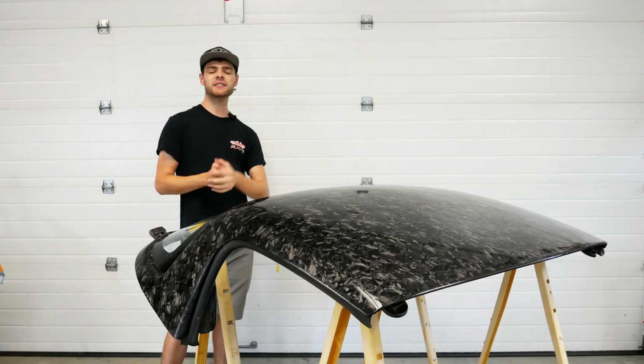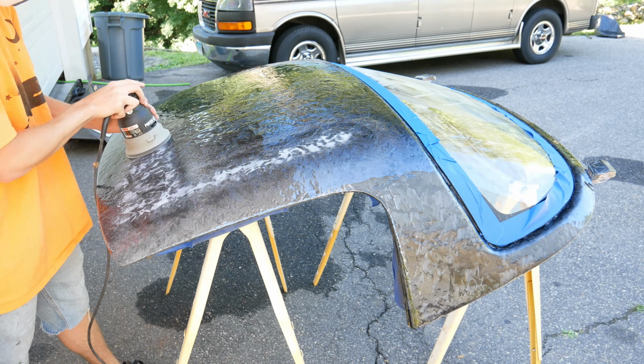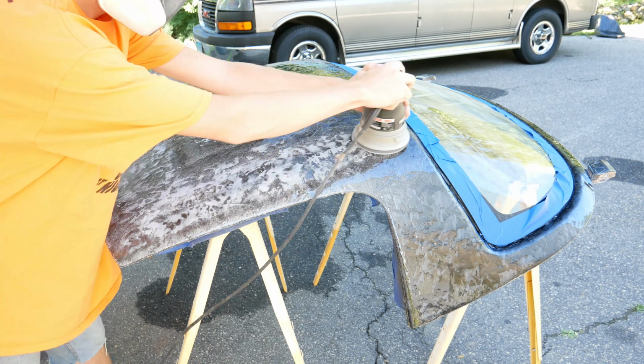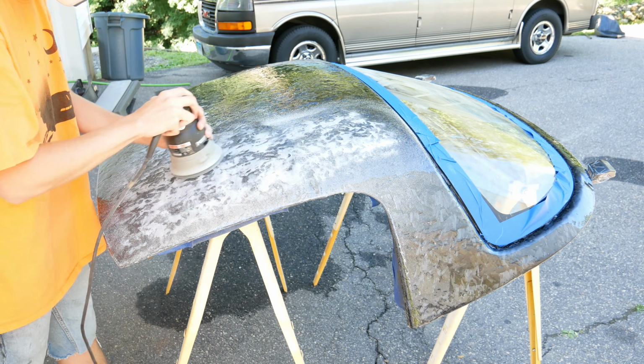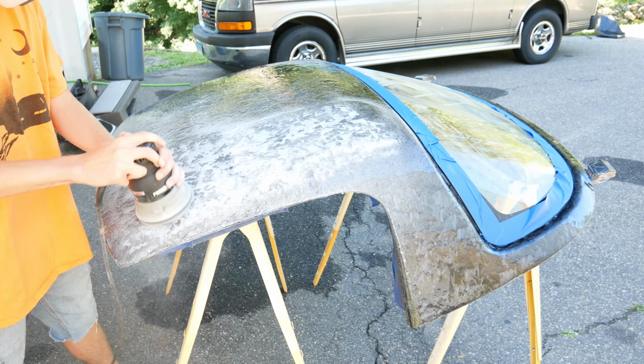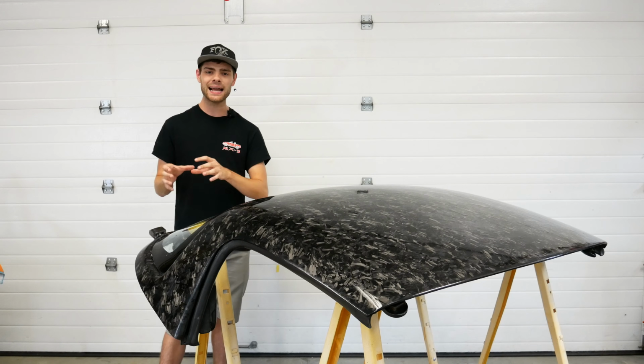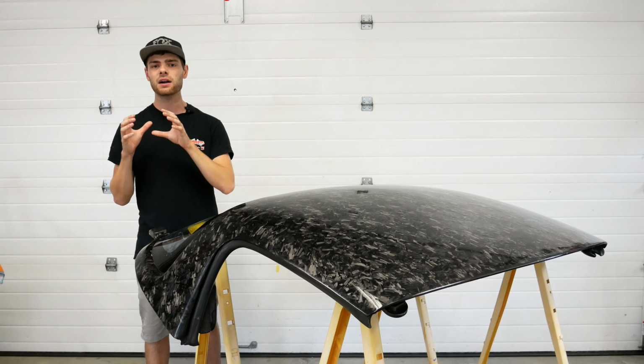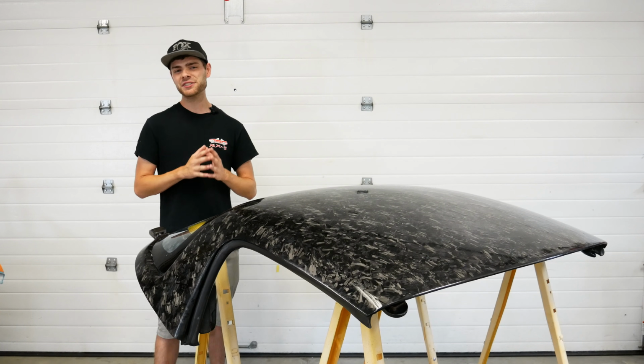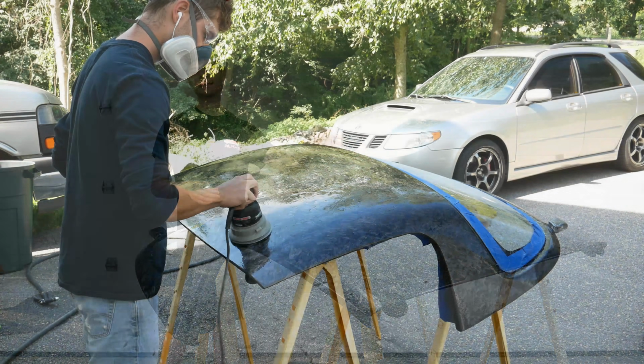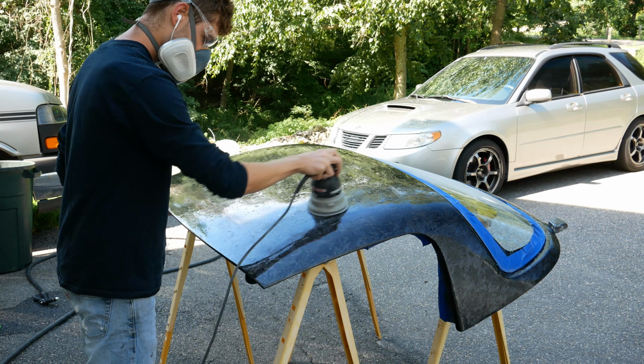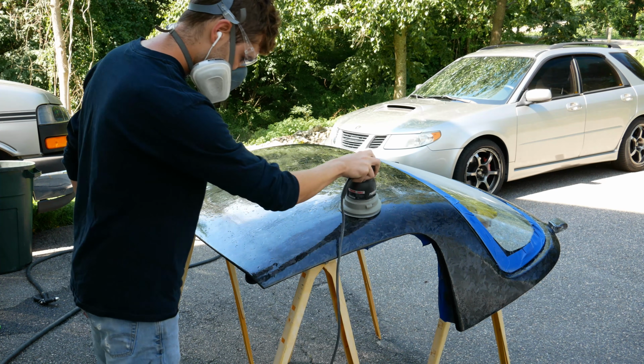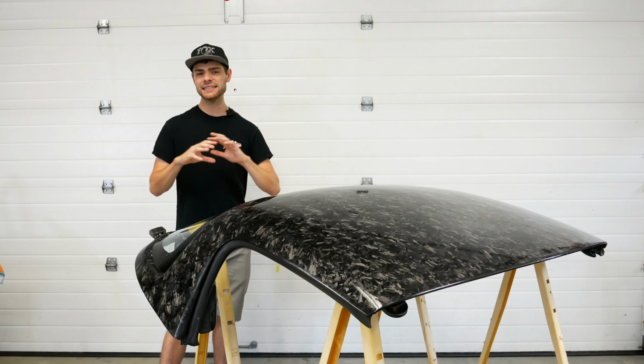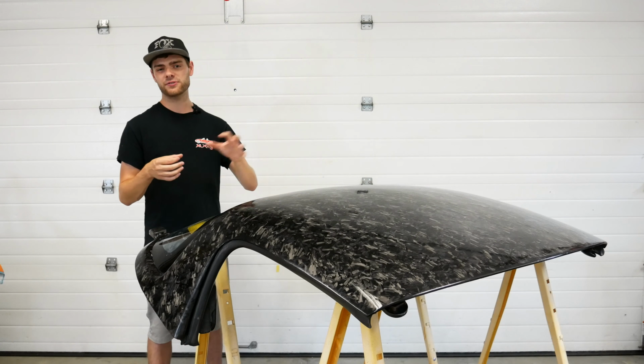I got the aggressive sanding disc out again and I flattened down this whole surface. Again, this takes a lot of time, but when doing wet layups like this without molds, it's a necessary step to get the results that you're really gonna want. And I ended up actually doing a third coat of resin and a third sand just because I wanted to get this thing as close to perfect as possible. Again, it's the same exact process for every coat here.